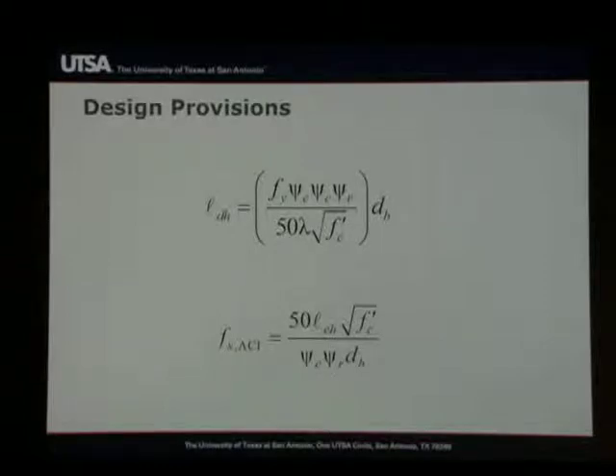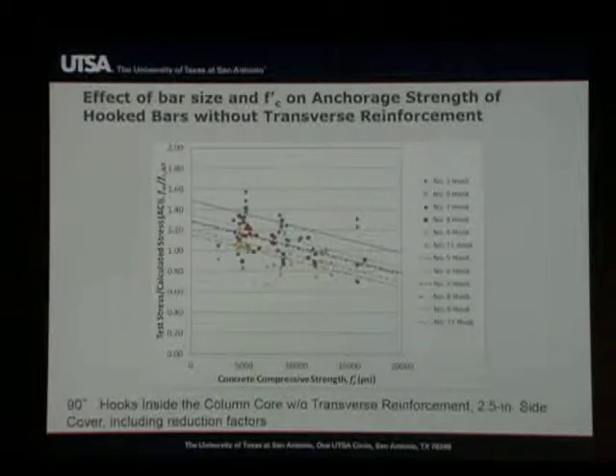The main difference is in the square root of f'c term. You're familiar with ACI design provisions. They place an upper limit of 10,000. So the largest number you're allowed to place inside that radical is 10,000. You're not allowed to take advantage of what happens between 10,000 and upwards of that. In the AASHTO code, when I read the provisions, I see that you're allowed to use strengths up to 15,000 psi, and I don't see any restriction on the square root of f'c term. And that's an issue of significance in light of the results from these tests.